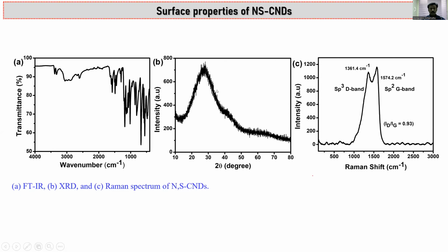Another one is the XRD pattern, which I explained previously. We get a peak at almost 25 to 26 degrees 2 theta, giving a d-spacing of 0.34 nanometer. The first is 0.34 nanometer, and another is around 40 degrees 2 theta, which is also a lattice plane. So from this we can confirm the carbon structure, which is related to amorphous carbon.